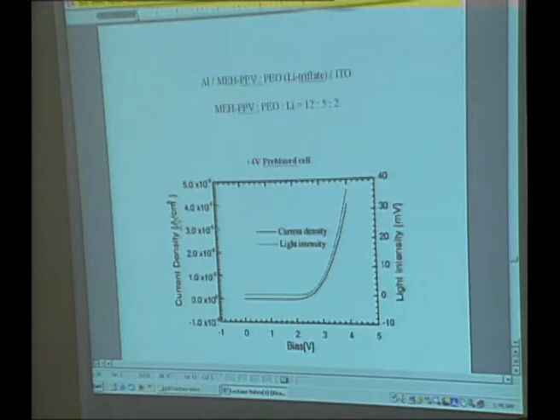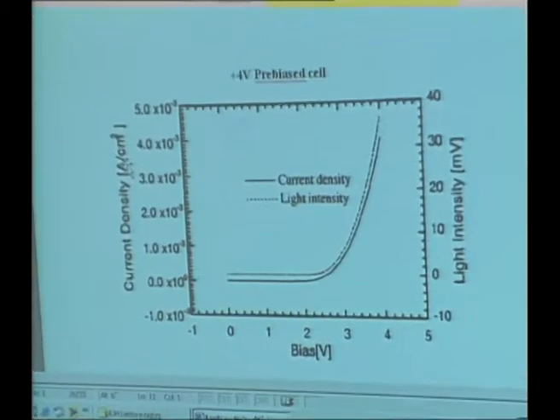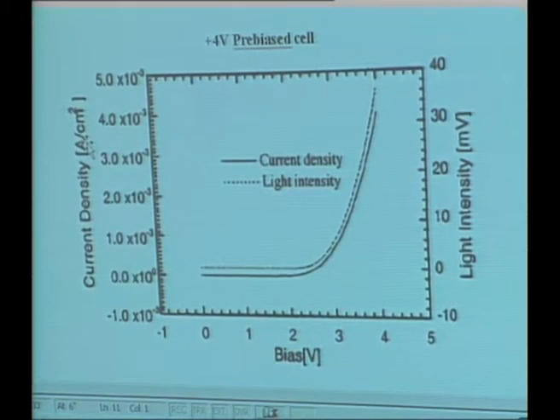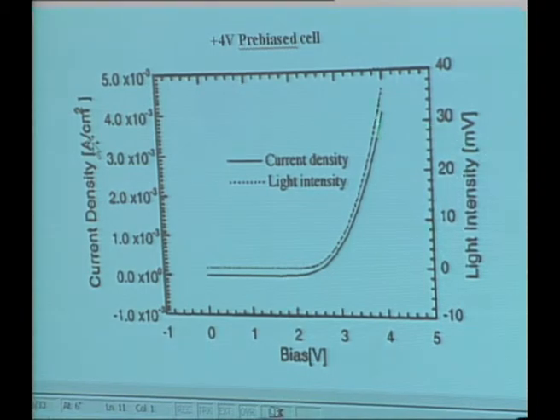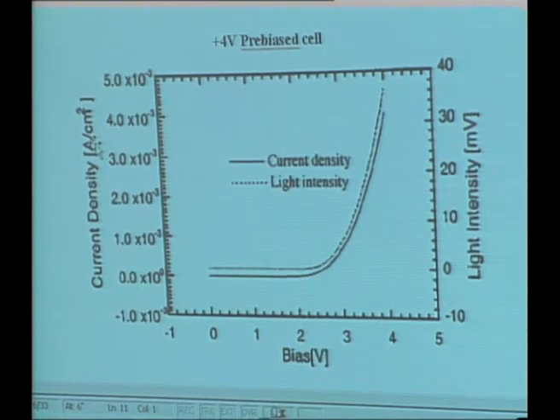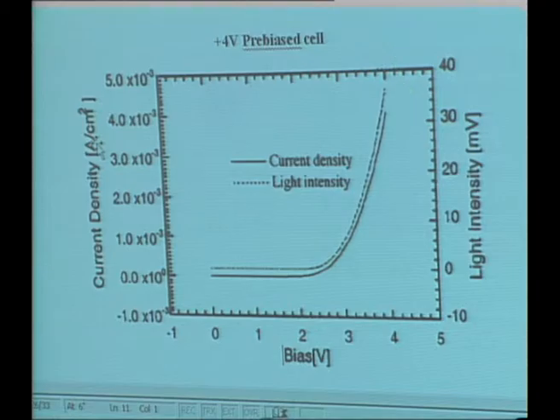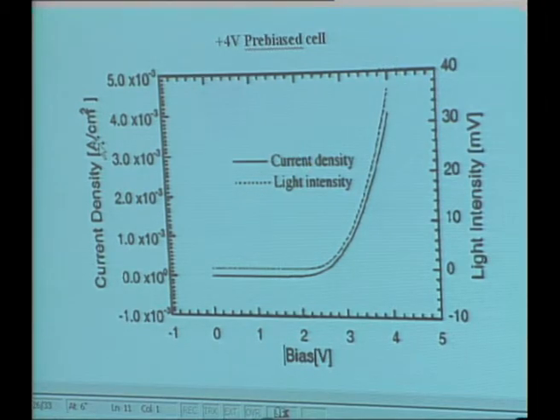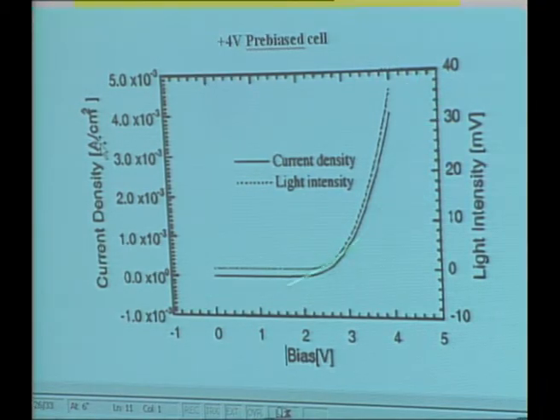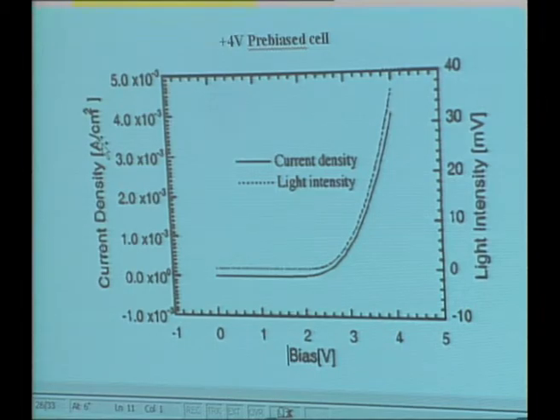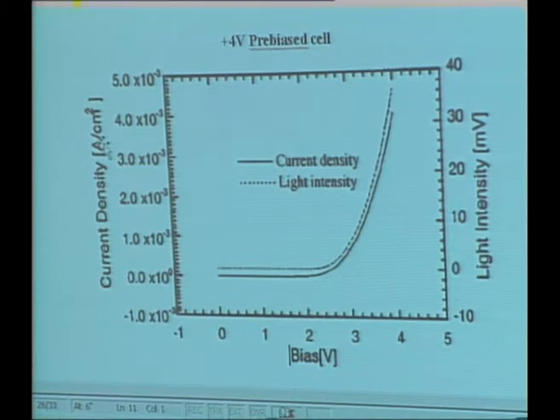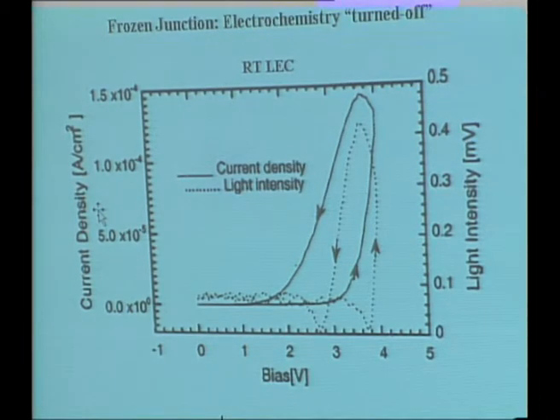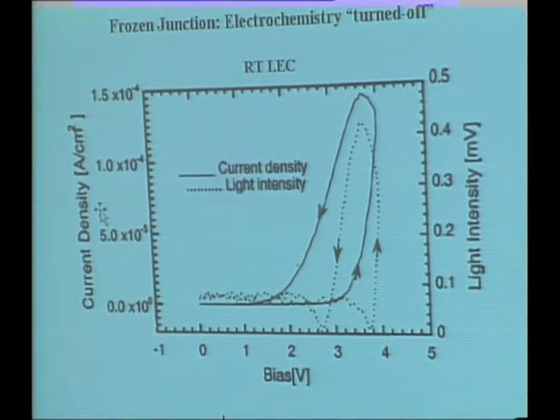Now, I pre-biased it at 4 volts and I cooled it down to 77 degrees. And now the IV curve is not symmetric. Now it's a diode, one way only. Now I get light out, and I can just go up and down on this curve because the ions don't move any longer.